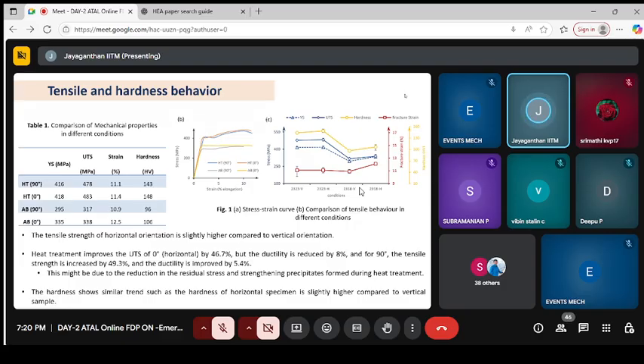I just highlighted how to produce 3D printed titanium added aluminum 2024 alloy. What is the role of titanium? The titanium is acting as a good grain refiner. The starting powder itself is being taken care of, whether it is 3D printable or not. So when you use the titanium added aluminum 2024 alloy for 3D printing, I end up getting a well refined microstructure for the 3D printed sample.